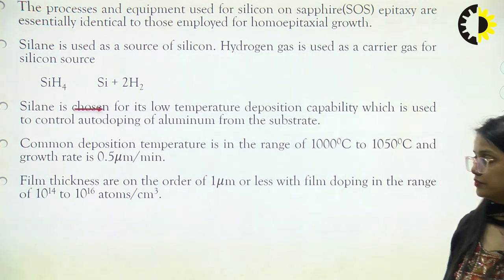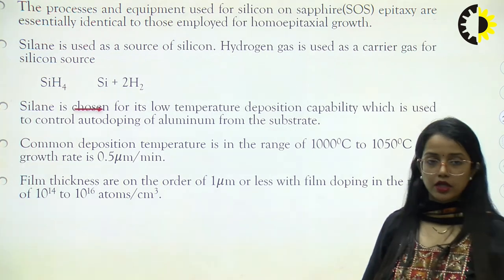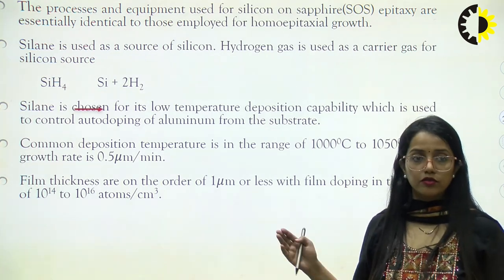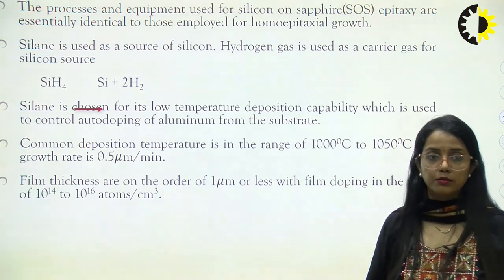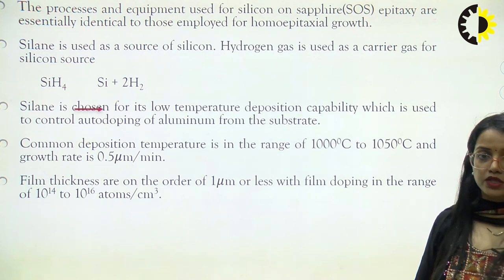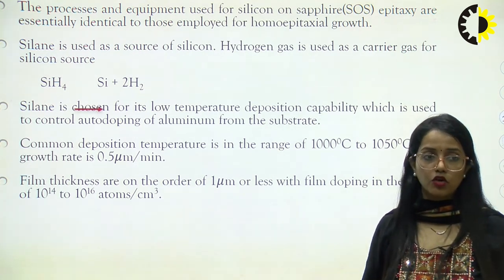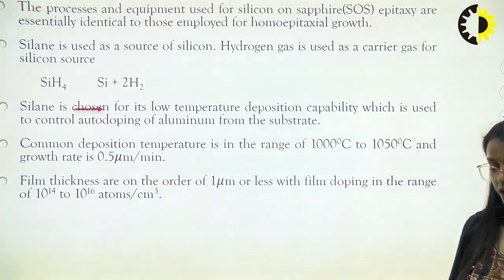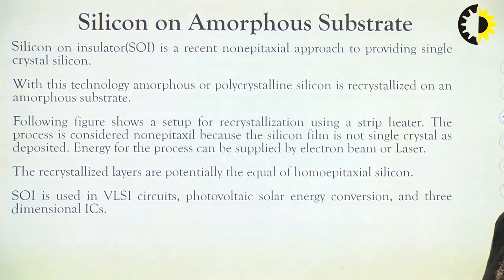The film thickness is of the order of 1 micrometer or less, and the film doping is in the range of 10^14 to 10^16 atoms per centimeter cube.